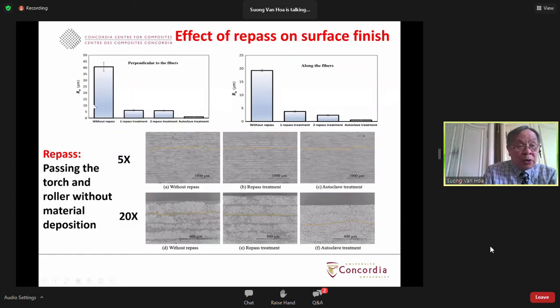So we show you the measure of roughness, Ra. If you make the part without repass, the roughness is about 40 micron. One repass reduces it down to 5, and so on. Compared to autoclave, it is about 1. Now, along the fiber direction, the roughness before repass is 20. After 1 repass it is 4, 2 repass 3, and then autoclave. Also, this one here shows you the microstructure. What we found is that the repass can also help to reduce the void content as well.